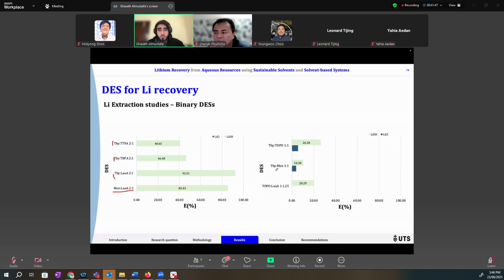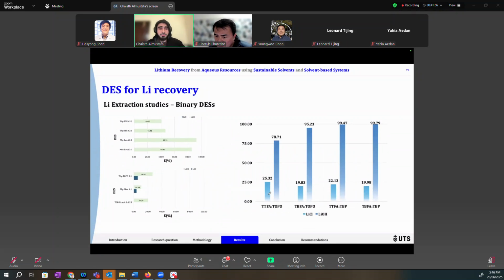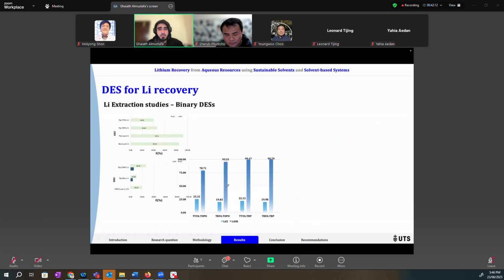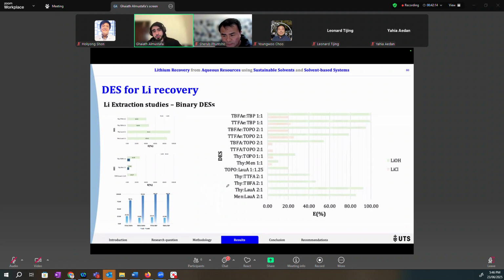So we want to understand exactly what is the effect of the solvent without the extractant. So we ran a lot of different binary combinations in order to find the pure effect of each component on its own. You can see that thymol-menthol on its own doesn't have any extraction efficiency. However, when you combine it with different components, you do have a particular extraction efficiency. And that was the case with other binary combinations. We compared them all together in order to identify which components can work for our case for lithium extraction.